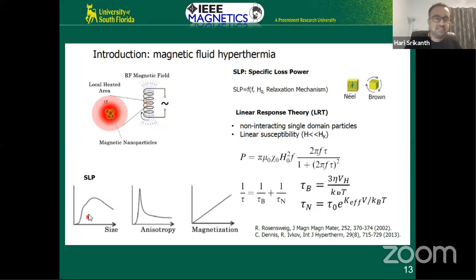Size is very important. It turns out that the best particles for hyperthermia are not too small, not too large. The highest power dissipation is actually somewhere in between. There's a sweet spot. So it is not actually single domain particles, and it's not multi-domain. Okay, somewhere in between. It's the transition between single and multi-domain.